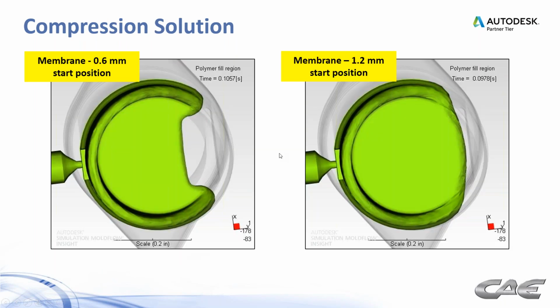So we came up with a different solution on this, and this was actually kind of unique in the sense that we're using compression on this. So what we did is we actually pulled back the core to make its starting position thicker, and we kind of iterated on that. We did one with a 0.6 millimeter start position and a 1.2 millimeter start position to allow that material to shoot through the membrane without backfilling or knit lines.